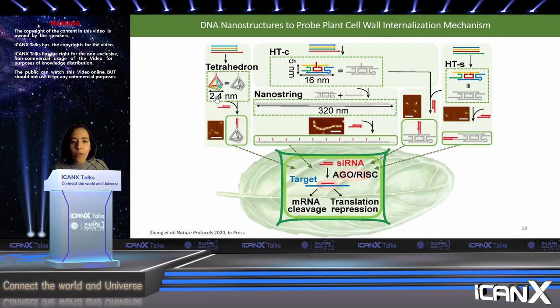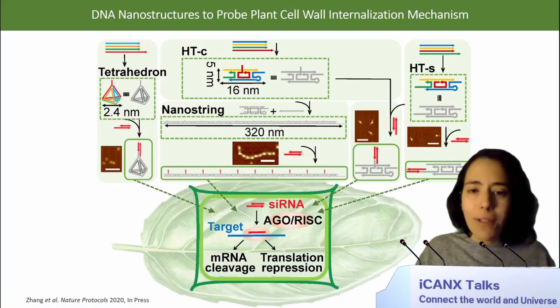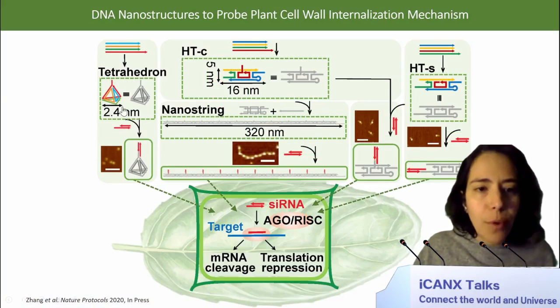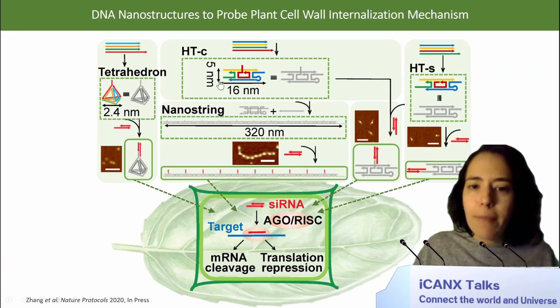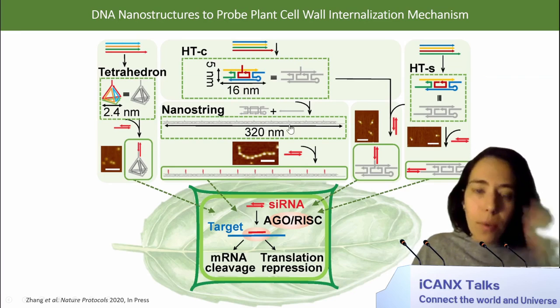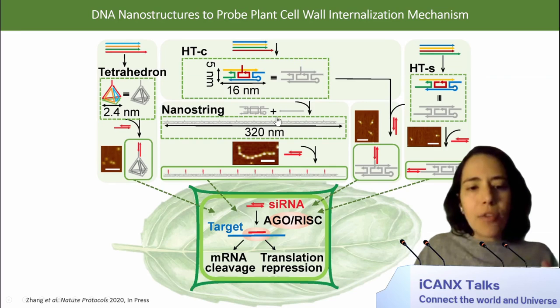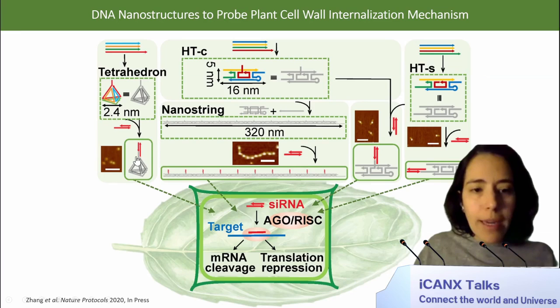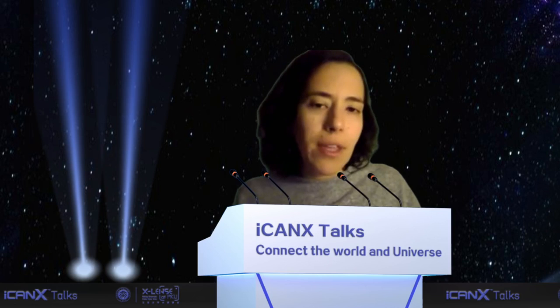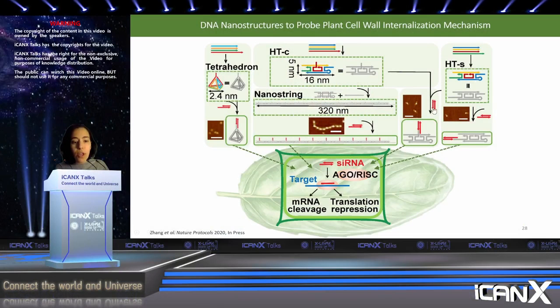In our case, what we made were a library of different shapes to test the effect of shape on nanoparticle internalization. For example, we made a 2.4 nanometer DNA nanostructure tetrahedra. We made 5 by 16 nanometer hairpin tile structures, and hairpins assembled onto nanostrings. Because these are DNA-based, we can also introduce loci onto these structures to attach DNA, RNA, or protein cargoes. Depicted by red arrows here, we attached a protein cargo, here neurotrophin protein, onto the vertex of the tetrahedron, onto the 10 monomeric units of the nanostring, or on the center versus the side of these hairpin tiles. We can confirm with high resolution atomic force microscopy that we are indeed attaching these protein cargoes to the loci that we predict.